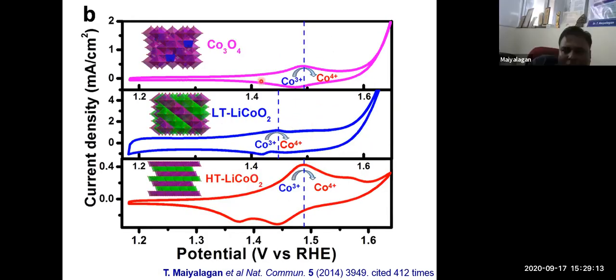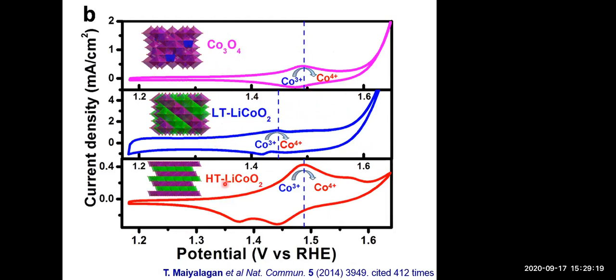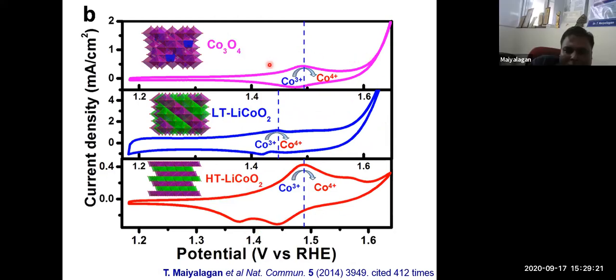we are electrochemists. We just check the oxygen evolution potential. When you look at the oxygen evolution, this is in 1 molar KOH electrolyte, an alkaline electrolyte. This catalyst, we are replacing this cobalt catalyst with the different structures, with the same spinel structure and layered structure. We just want to replace the platinum and the iridium. That is the idea. So when you put it in potassium hydroxide, this is a cyclic voltammogram. You look at it, there is a redox couple of 3+ to 4+, and this region above 1.6 volt is the region where the oxygen evolution reaction takes place.